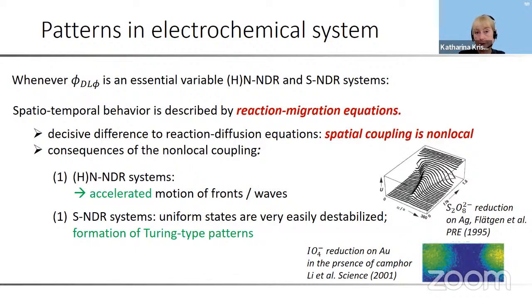This makes it rather complicated. You do get then an equation you can formulate for the double layer potential in a closed way. I'm not doing it here because it is mathematically a little bit involved, and I don't think we have so much time for this short, tutorial type of lecture. But what you arrive at is what we call a reaction migration equation for the evolution of the double layer potential. What is important is, what difference does it make that we have a reaction migration and not a reaction diffusion equation? A diffusion equation is always a local coupling, so it's a next neighbor coupling.